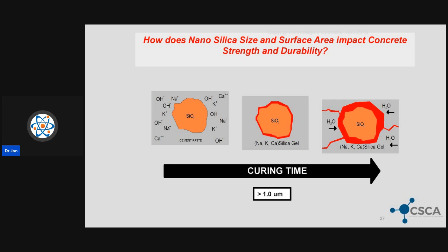Now, what's great about that stuff is it has an immediate interaction with the pore water solution, doing something that would otherwise cause ASR expansion. And there are some wonderful papers that I've been reading on the role of portlandite or calcium hydroxide, the need for that for the ASR gel expansion to really kick off.